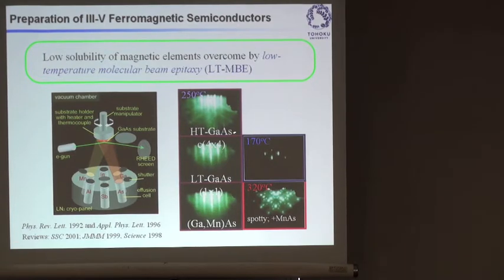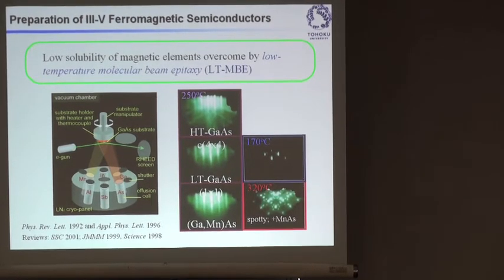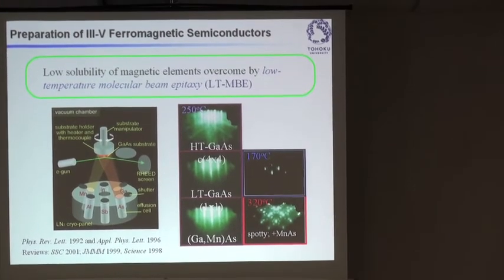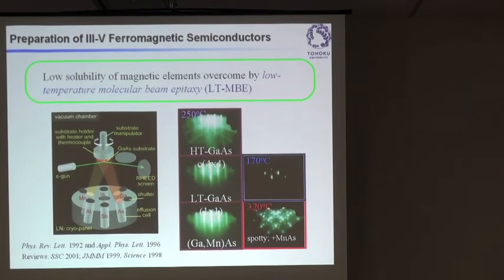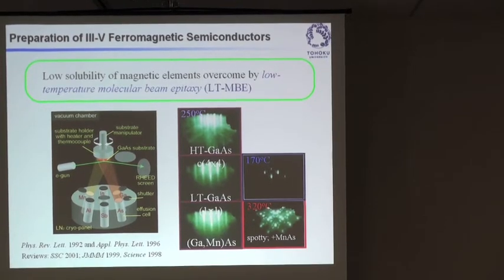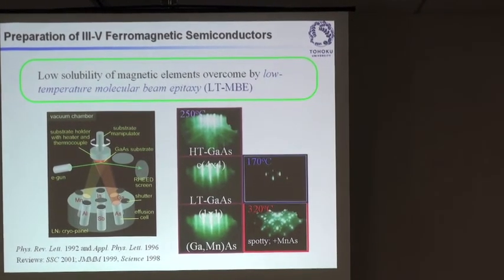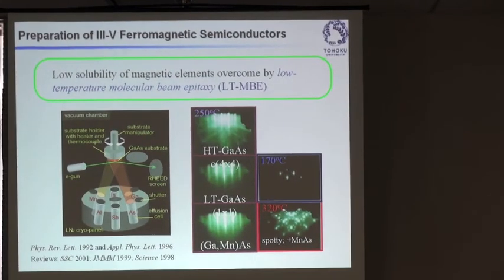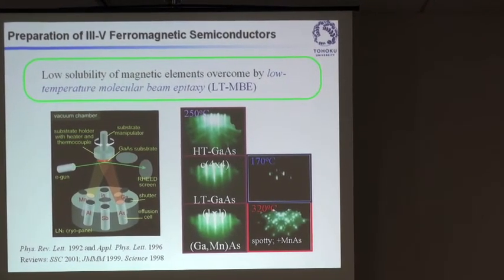If you choose 170 degrees C, we get polycrystalline growth. And if the substrate temperature is too high, then we found that manganese arsenide grows. Manganese arsenide is a stable form between manganese and arsenic. So in between 300 and 170, we can grow very nicely a gallium manganese arsenide epitaxial layer. So that was the beginning of the whole story.